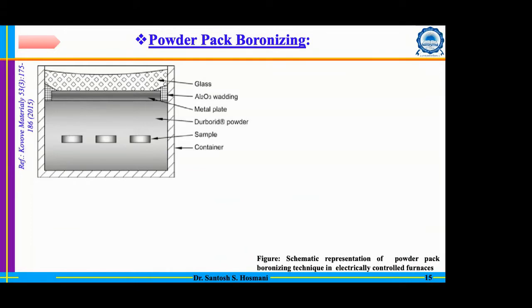Otherwise, it's very difficult to control the boride layer thickness, and you really cannot predict what will be the scenario in pack boronizing. So you need to adopt a particular sequence. What we used to do in our container is that about a 20 millimeter layer is deposited of this boronizing mixture, and we keep the sample over it. Then again we have a 20 millimeter layer of this boron powder, followed by the alumina powder, even silica, as well as glass powder.